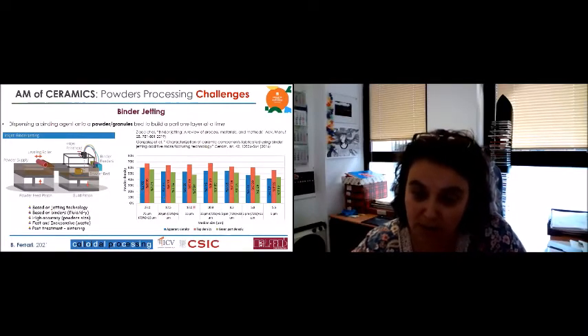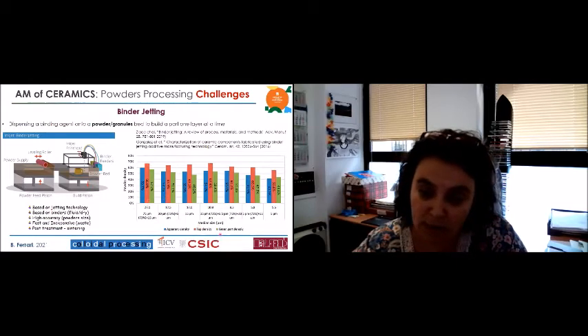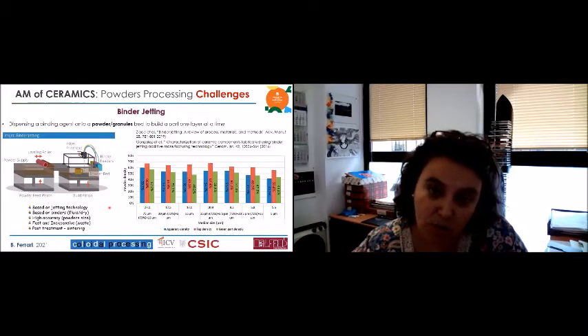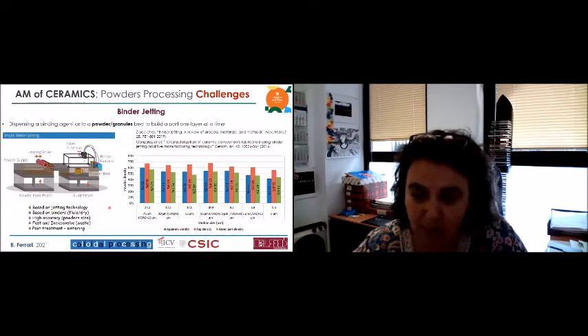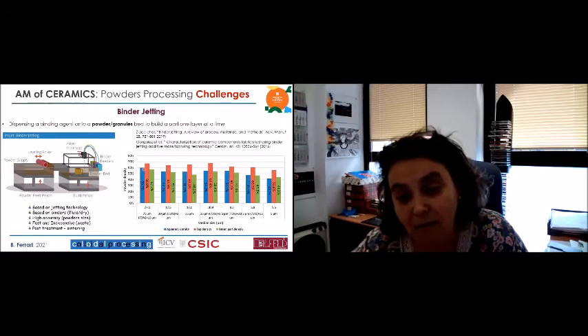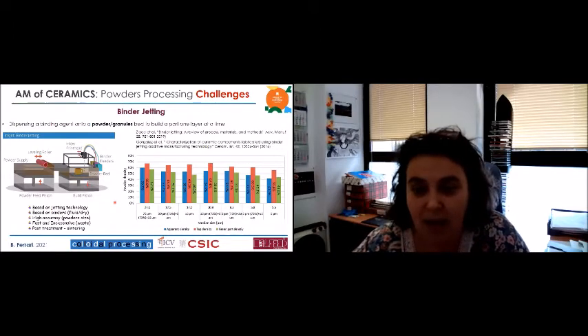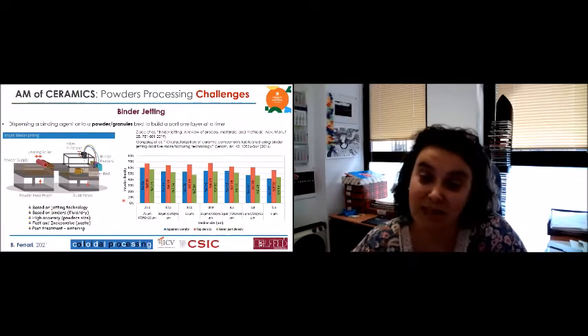And when you tap this powder, that is the red one. And when you are promoting or forming or shaping the green part, you are going to see that when we tap, that means when we try to improve the fluency and compact this powder by tapping, we have the highest density in green, even better than when you put polymer in. So what does that mean? That means that we need to improve the fluency of this powder.